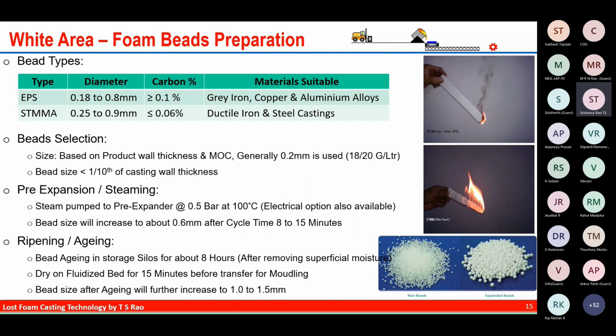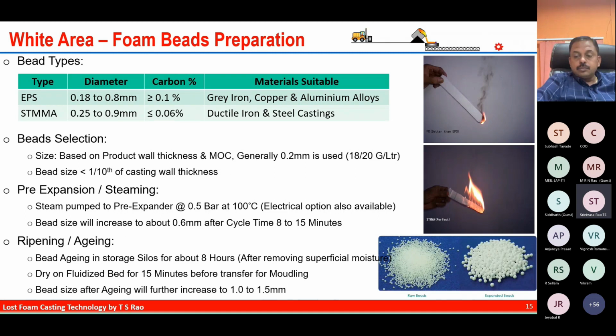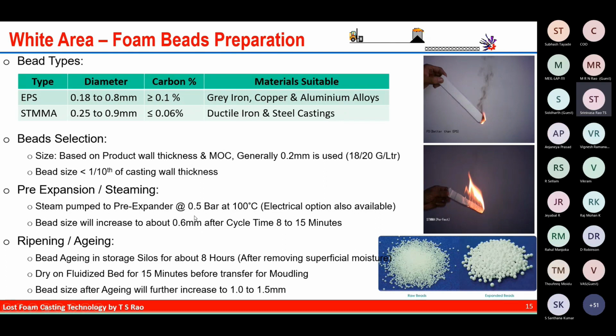And once the beads are selected, the next process is called pre-expansion or steaming process. The beads are taken into a steam boiler, and the steam is pumped for pre-expanding the foam beads at a half bar pressure at 100 degrees centigrade. A few electrical options are also available today in the market. The bead size will increase about 0.6. When you take 0.2 as the initial bead, after pre-expansion or steaming, the size goes to 0.6 millimeter. And the cycle time again depends on the bead's quality requirement. It will vary from 8 to 15 minutes.